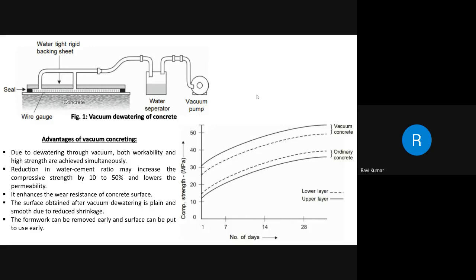After the requirement of workability is over, the excess water will eventually evaporate, leaving capillary pores in the concrete. These pores result in high permeability and less strength in the concrete. Therefore, workability and high strength don't go together, as the requirements are contradictory to each other. However, with the technique of vacuum concrete, both are possible, that is workability and high strength at the same time.